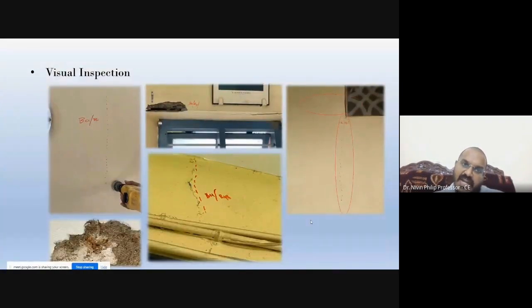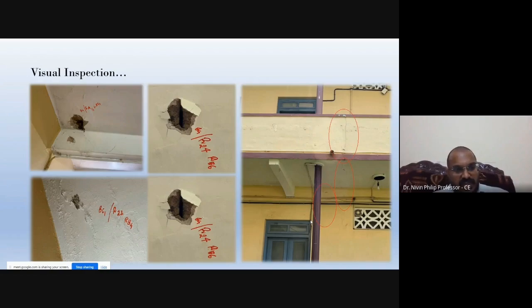In the visual inspection, we identify what type of cracks are there. We collect samples of the materials and identify the locations of deterioration. Wherever there is a crack, we have to mark it and identify how much the crack has propagated, to what extent, whether it is extending to the foundation, and whether any delamination or spalling has happened. We have to identify everything by visual inspection, and if any moisture is present or any corrosion-specific spalling has happened, we have to identify and mark each endpoint.